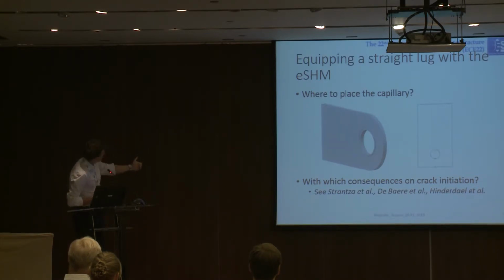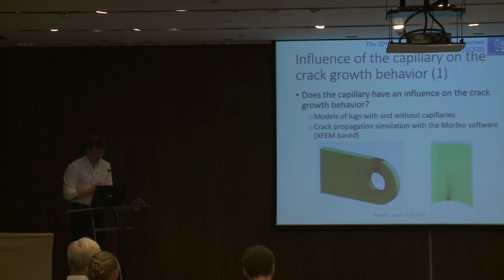So this is why you see here a cut view of the lug, and maybe it's not very clear, but you see all around the capillary that has been installed. To be more clear, you have on the right a cut view of the top part of the lug, and you see the rectangle of the lug, of course, and you see the capillary. Of course, due to the fact that you include that capillary in your structure, you modify that structure a bit. So the question arises whether on that cross-section you will have a different stress field. And the question is whether the capillary influence is so much that you will have an impact on your crack propagation life. And this is in particular what we wanted to study.